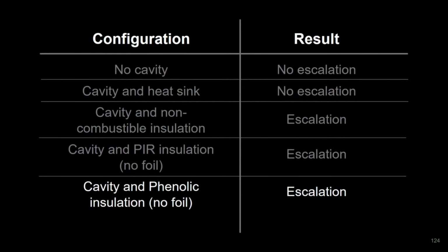I then undertook similar experiments, this time with Kingspan's K15 phenolic foam insulation product. Again, I removed the foil facing from the insulation. And again, I found that the results were very similar to the case of PIR with no foil facer. Escalation occurred, and again, it occurred more quickly than for the non-combustible insulation case. I observed that the K15 continued to smolder for some time after escalation, and in some cases continued flaming for quite some time. The Celotex PIR foam did not display this behavior.